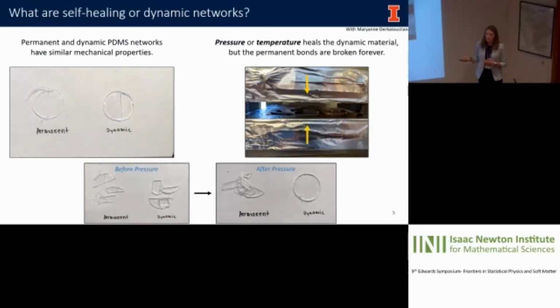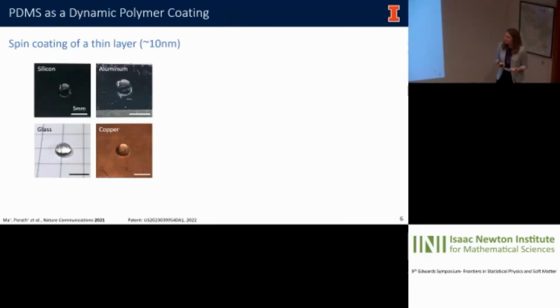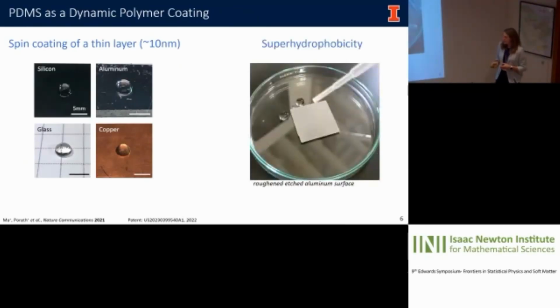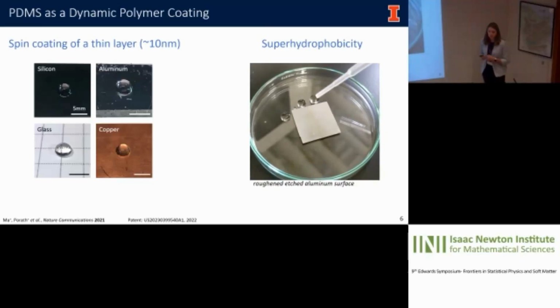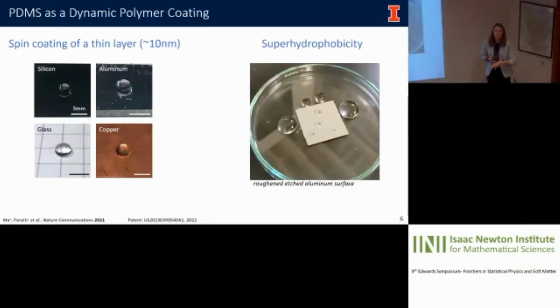So I take this dynamic PDMS and I spin coat it onto a couple different substrates. It's very versatile. And if I even spin coat it onto a roughened aluminum surface, the hydrophobicity of the PDMS combined with the rough surface allows for us to achieve super hydrophobic capabilities as well.